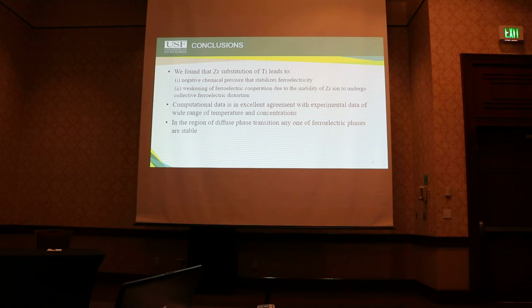So in conclusion, we found that the substitution of zirconium for titanium leads to a negative chemical pressure, which is ferroelectrically favorable, as well as a weakening of the collective distortion of the cell, which is ferroelectrically unfavorable. Using these two effects in our computational data with the modification of the effective Hamiltonian, we were able to accurately recreate the phase transitions of BZT, which leads us to conclude that they are the primary factors for the phase evolution. As well, in the region of the diffuse phase transition, any one of the three ferroelectric phases are stable, and we conclude that this is the result of the diffuse phase transition.